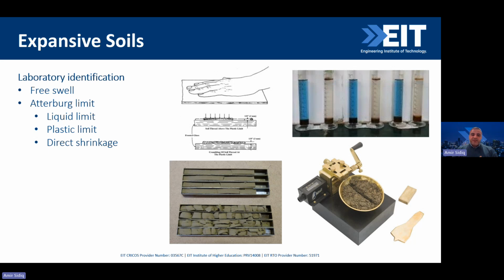Then we have typical tests to understand, according to the standard, the clay behavior. So we have the Atterberg test. Basically, we find the liquid limit, find the plastic limit, and then from the liquid limit and the plastic limit, we find the plasticity index. We have the linear shrinkage. Also, we have the free swell to understand the characteristics of the soil. That gives us a hint. It could be some simple calculation or some graphical identification, which provides us the expansiveness of this particular clay.